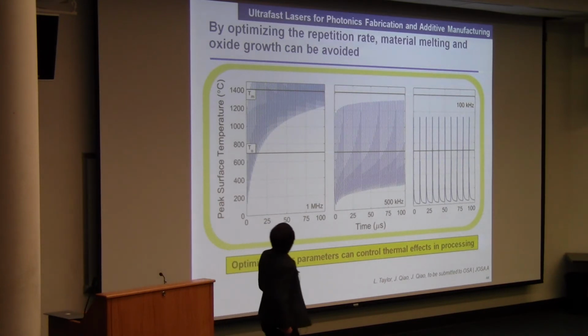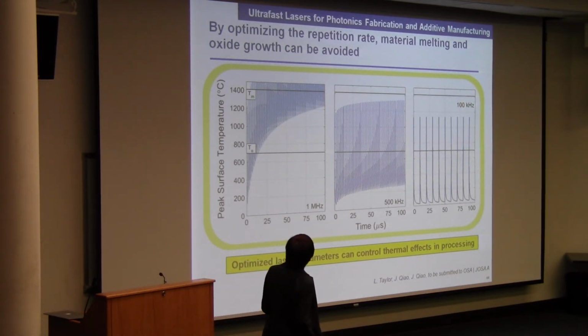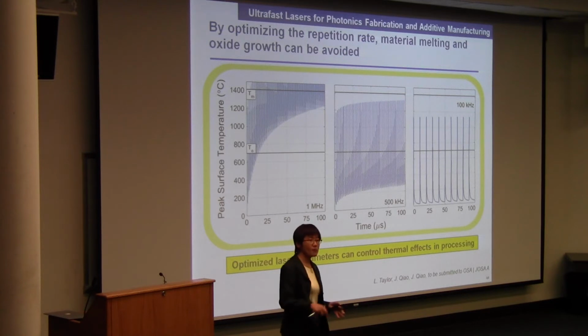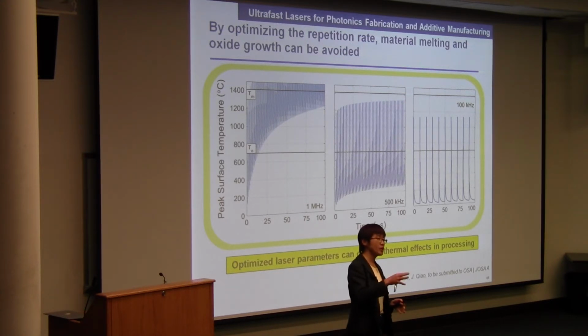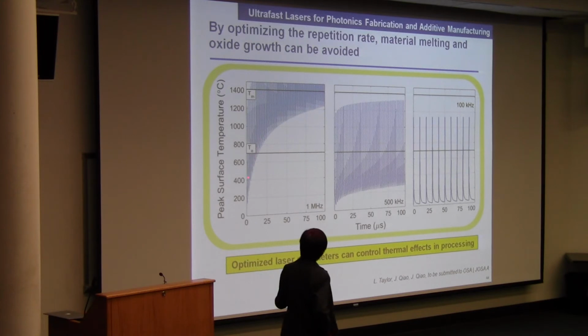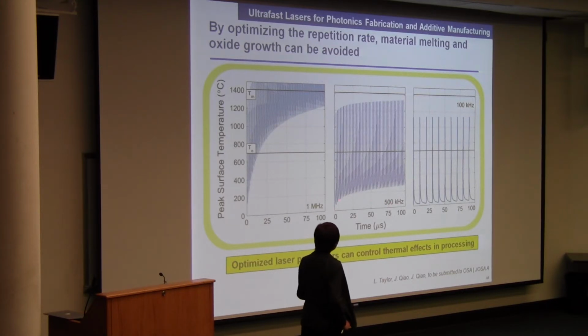So to continue, by optimizing the repetition rate, the material melting and oxide growth can be avoided. So we continue with the model, developing an optimization process to vary the repetition rate and vary the scanning speed. So we construct a matrix to develop optimized laser parameters to have deterministic laser processing. And thus you can see that if we operate at 1 megahertz, we're going to exceed the oxidation temperature. We're going to be very close to the melting temperature. But when we operate at 500 kilohertz, we are much below. The relaxation temperature is much below the oxidation temperature.